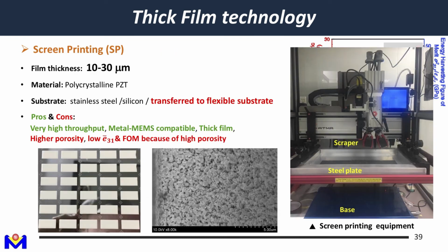Okay, so screen printing here, again, theoretically you can get around 48 gigapascal. But for screen printing, you have to have the PZT powder mixed with a certain kind of organic solvent to make it like a paste or like an ink, so you can print it. And again, when you do heat treatment, all this organic solvent will evaporate and create cracks inside the material. You can see some cracks. So overall speaking, the piezoelectric property, or we say the figure of merit, will degrade a lot compared to aerosol deposition or bulk material. And the thin thickness you can fabricate with this method is around 10 to 30 micron.